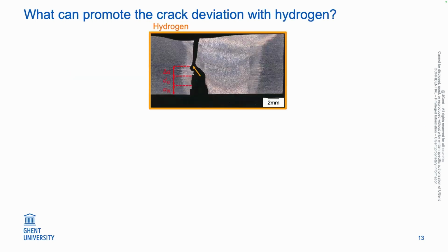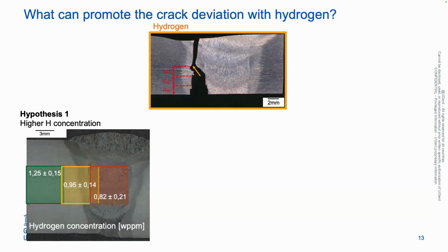Now we question why this happens. Why do we have this deviation of the crack? The first hypothesis is, if we look at the hydrogen concentration, we already had a different distribution of the hydrogen concentration, because we extracted cubes of 6 by 6 by 6 and charged them under the same conditions which were used for this test as well. And we saw different concentrations for the base material and for the heat-affected zone and the weld material.